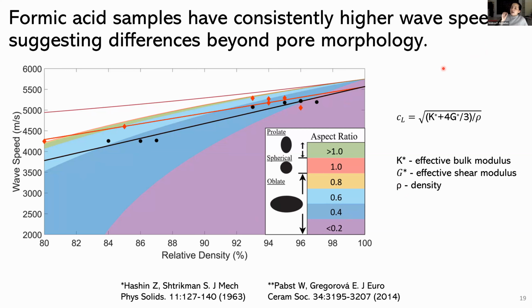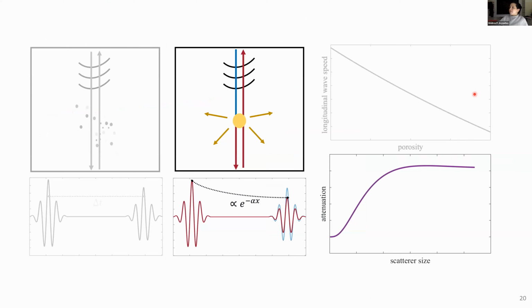So if we have stronger bonds between the grains, we might essentially be getting a larger effective modulus for the samples that were processed using formic acid. So again, part of what this illustrates is that the samples that were processed with a different liquid phase are going to have different effective properties. And this can help us identify different parameters that we can change in that manufacturing process and understanding how these parts behave. Which then brought us to the analysis of some of our ultrasonic data.